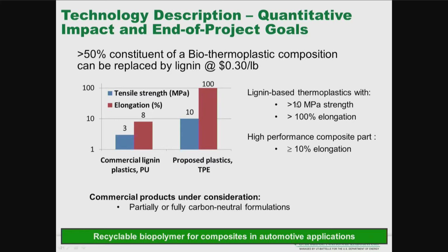And our target was, can we make lignin-based thermoplastic greater than 10 MPa and more than 100% elongation? So this is almost like a thermoplastic elastomeric material. And of course, at the end, we have to demonstrate composite part with greater than 10% elongation. That would be a tough product, and that is a very tough goal too, and we are currently working on that. So if you look at commercial lignin-based plastic, polyurethane and other foams, they produce very weak, brittle, porous material, and those are very low in mechanical property. For example, 3 megapascal tensile strength and even less than 10% ultimate elongation. So our goal was to get 10 megapascal strength and 100% elongation.